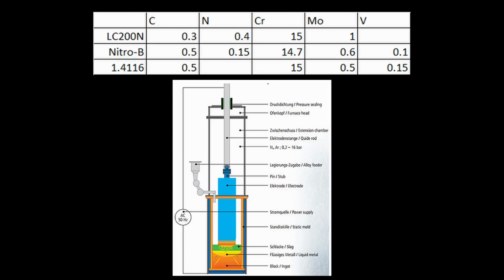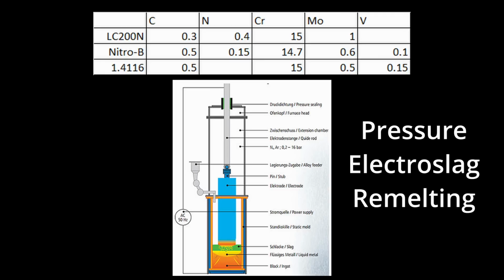So those other steels max out around 0.1 or 0.15 nitrogen, but they use a technology called pressurized ESR so that they can get more nitrogen into the liquid steel using high pressure. Yeah, because this stuff seems like it has a freakish amount of nitrogen compared to these other ones, huh? Yeah, it's difficult to get that much nitrogen in there. So 0.4% around there for LC200N. And everything we've seen so far says nitrogen's doing some good work. So mo nitrogen, mo better.